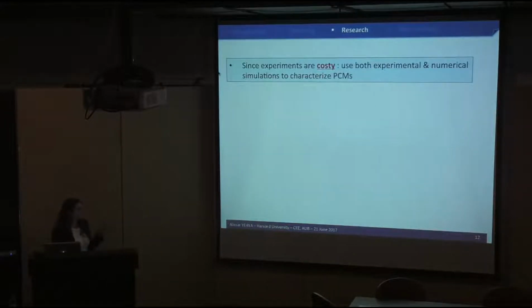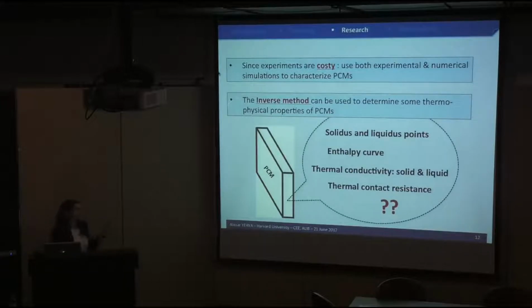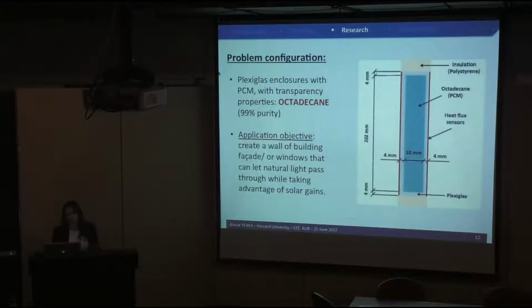Since experiments are costly, we adopt an experimental and numerical method at the same time to characterize these phase change materials. Most of the time we use the inverse method to predict properties that can't be directly obtained experimentally, especially, for example, the degree of supercooling, the enthalpy curve that we've talked about, or even the thermal contact resistance between the enclosure and the material. They can't be directly inferred from experiments. We need some numerical work.